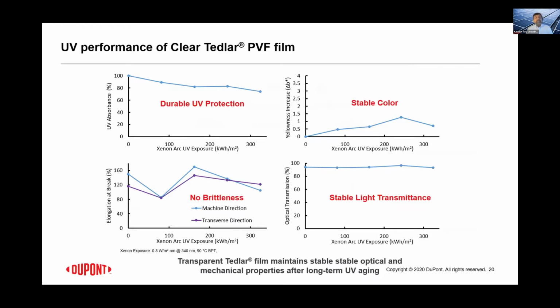Once we have the initial properties, then it's time to look at how these properties hold up versus accelerated aging. So I'm showing here quite a bit of data. On the top left over here, we are showing UV protection and UV absorbance as a function of exposure. So what we are seeing is the overall UV protection is pretty stable, and stays pretty stable well over 300 kilowatt hours of xenon exposure. And this is beyond what the backsheet would see over a lifetime of 25 years. So that gives us confidence.